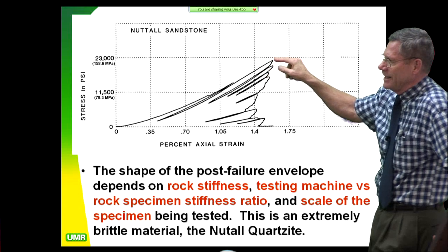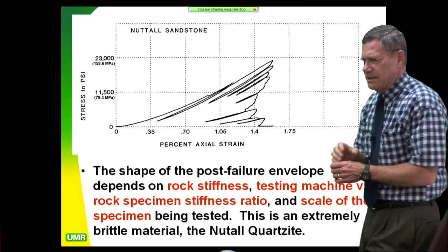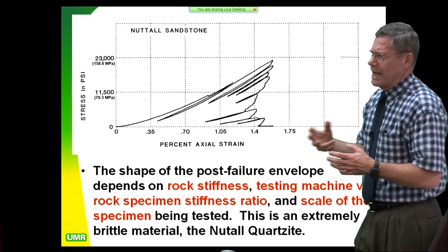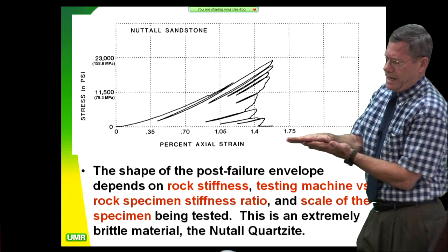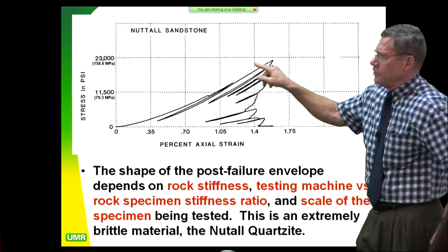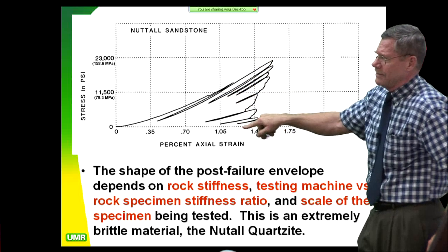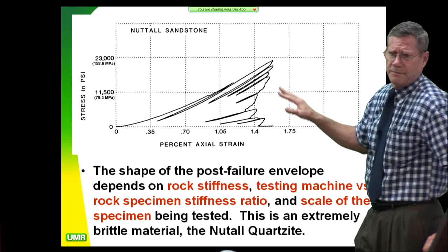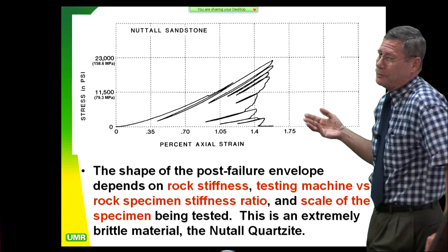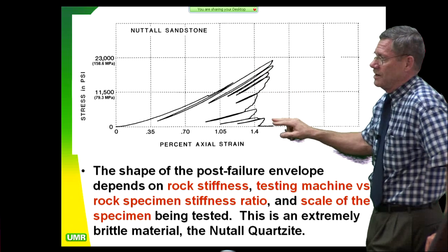That is nasty stuff. And of course, the contractor got in there, and the Nuttall sandstone had a lot of mica in it. It's a very old unit, but had a lot of mica, and he could rip that because mica's got very low strength along the planes of the foliation. But when you get into something that had no mica and it was a pure quartzite, that's a hardness of 7, and it'll beat up your equipment something fierce, because your equipment, your hardened steel, is 5.4 to 5.6, and this is 7. So it really beats up the equipment very bad.